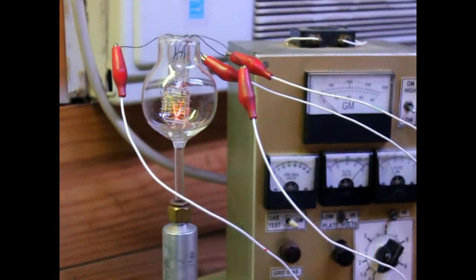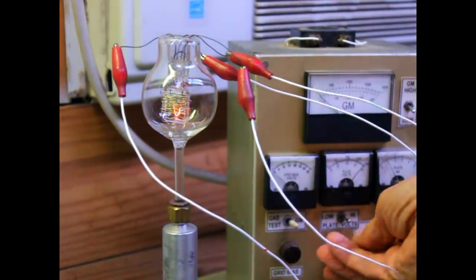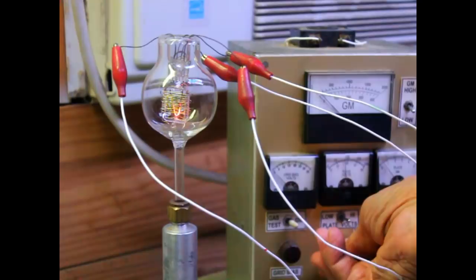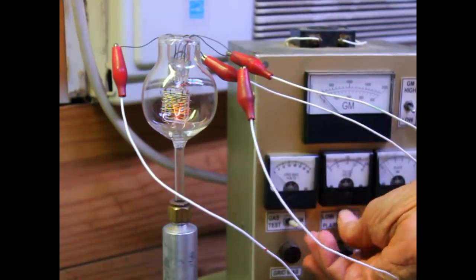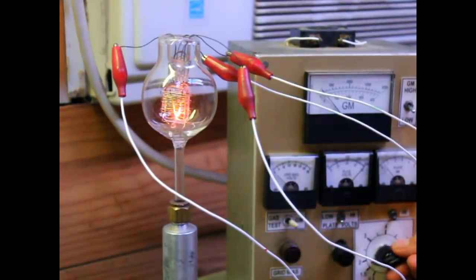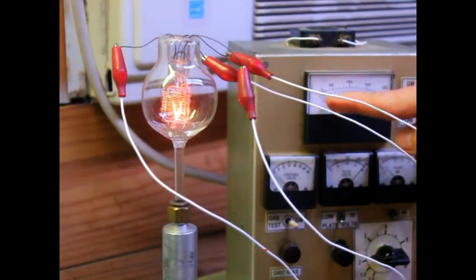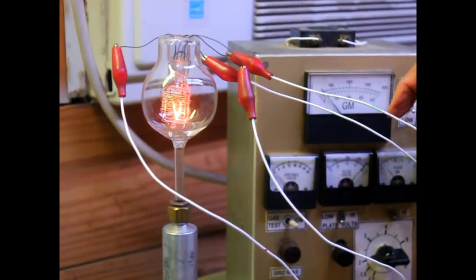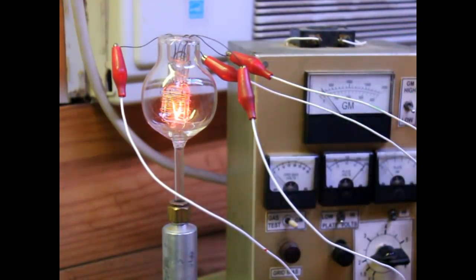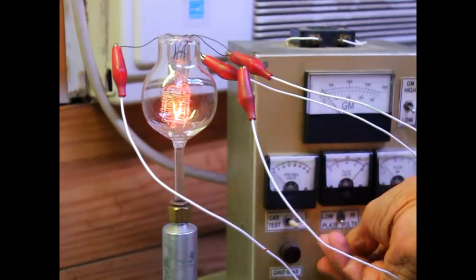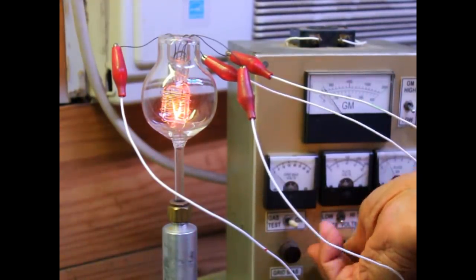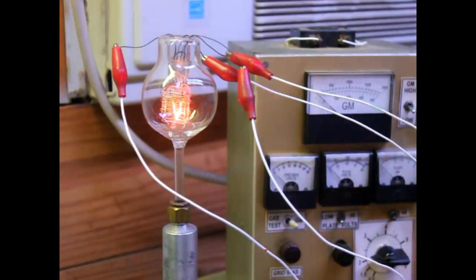Turn it off. Even with fairly low filament voltage, we're getting about 1 milliamp of emission. But when we cut that voltage down, well, we're getting it. Okay, that's 90 volts. Let's see what we get with 90 volts. Okay, with our 2.5 volts, we're getting about maybe a 45 transconductance, but we don't get much plate current. It takes that voltage to bring that current up and get the transconductance. Okay, so the tube is a success.